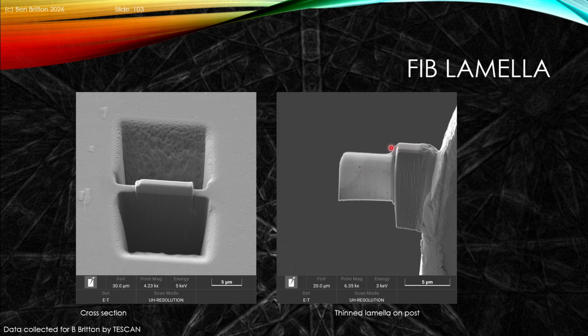So we've got the platinum cap that's been reduced after the thinning process, and this sample is probably less than 100 nanometers in thickness. What's super nice is you can see there's a grain boundary and a series of precipitates, and this is just showing us in the SEM under the ET detector. And we'll see that we can do improved analysis by using, say, a STEM detector or moving it into a TEM.